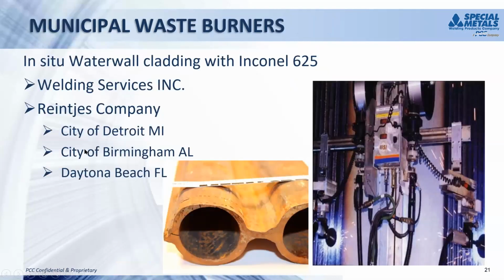Next slide. One of the first places that it was really used in industry, which I believe goes back to the 70s in the United States, was the municipal waste burners. Historically, these water wall tubes were made with a low alloy steel, something like a 2 1/4 or 1 1/4% chrome alloy. And that worked fine under most situations. Then we started burning some of the municipal waste.